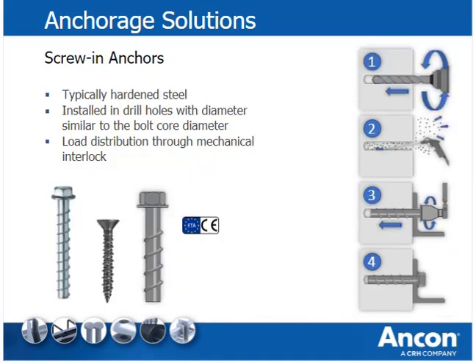Screw anchors, also called concrete screws, are installed in holes that match the diameter of the screw shaft. The hardened threads of the screw cut into the wall of the borehole and create an interlock between the screw and the concrete over the entire length. The drill hole has to be deeper than the length of the screw to provide room for the product of the thread-cutting process.